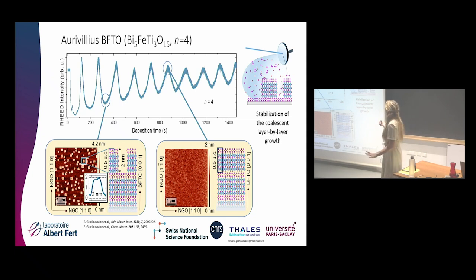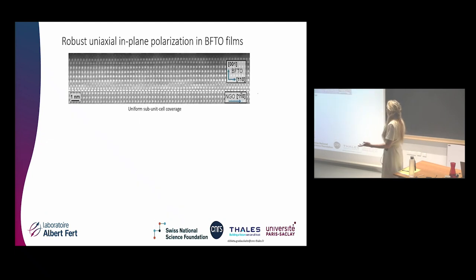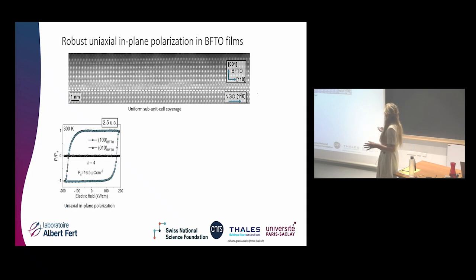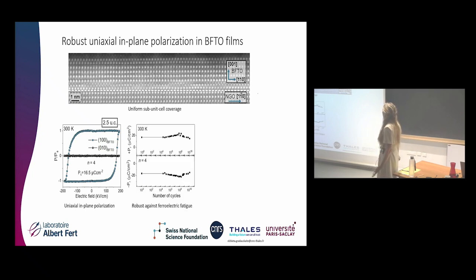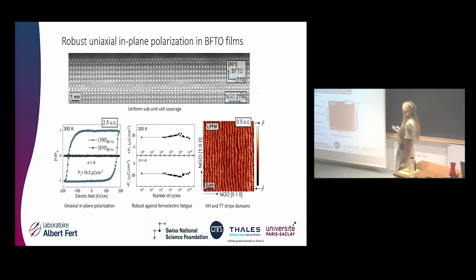So we realized, okay, we can have something that's very nice, uniform, covering our substrate. And we could show that already at 2.5 unit cells, we can have some nice polarization switching in the plane in these materials, good for electric fatigue performance. And most importantly, even at half a unit cell, these materials are already ferroelectric. So this is lateral piezoresponse force microscopy, where we're looking at the ferroelectric domains, and we see that already half a unit cell has clear striped domains.